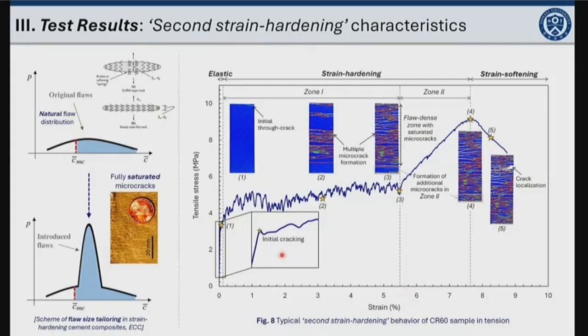After initial cracking here in the matrix, a general slow strain hardening behavior was observed up to a strain of about 5.5%. For this reason, multiple microcracks could be fully saturated in the flaw dense zone with enough crumb rubber.